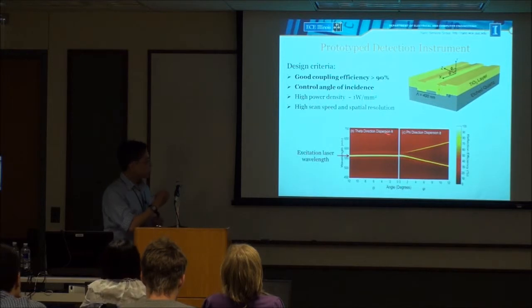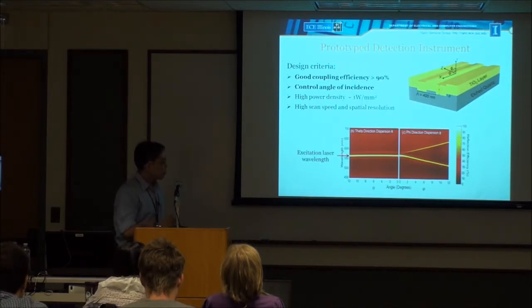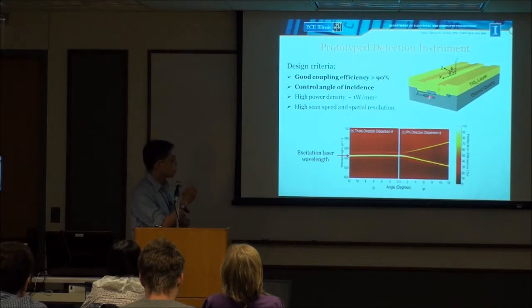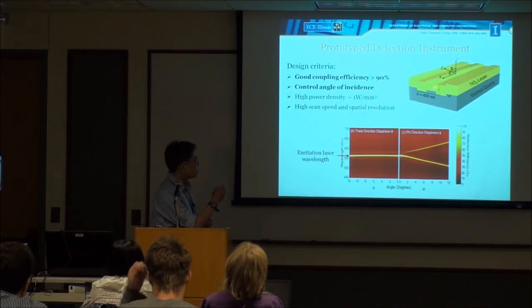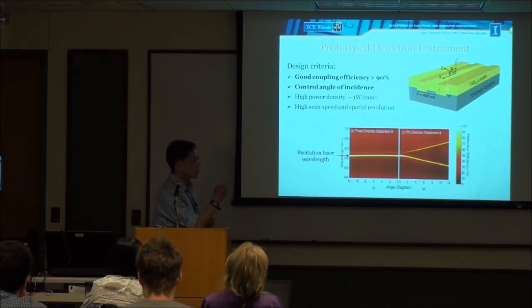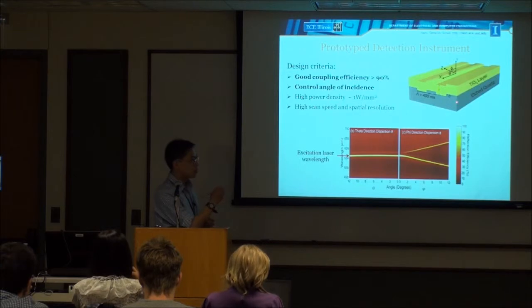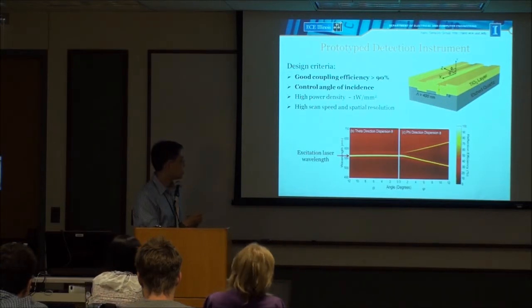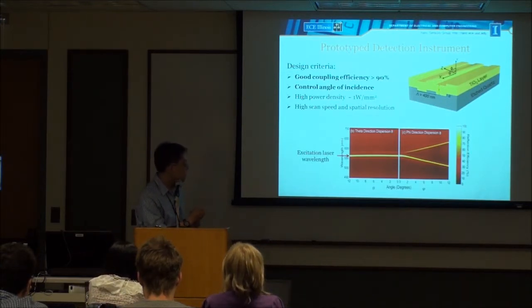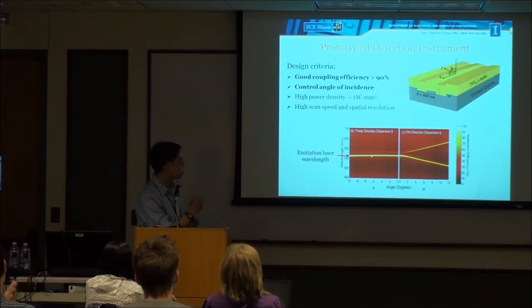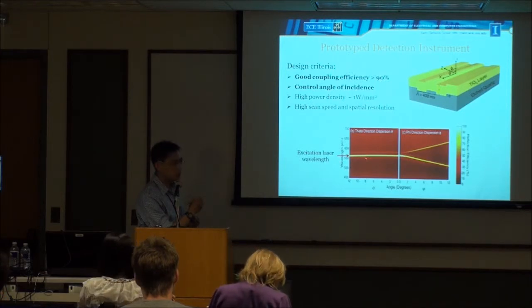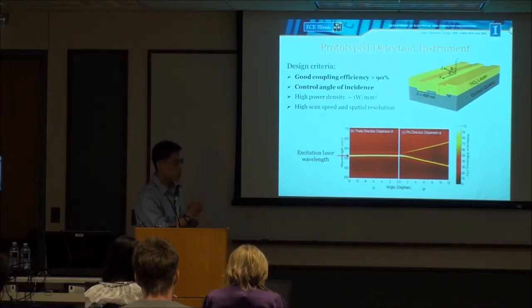So those two figures show the dispersion relationship of this one-dimensional photonic crystal structure. The left one is measured when we change the incidence angle along the theta direction. We illuminate the substrate with broadband light and measure the transmission and reflection spectrum. When we change the angle along the theta direction, since there's no variation along the grating, it's uniform. So this is what we see: the reflection wavelength is independent of the angle of incidence.